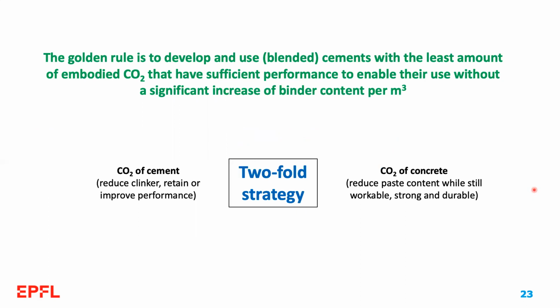Personally, I consider that the golden rule is that we need to develop and use blended cements with the least amount of embodied CO2, which in most cases is proportional to the lowest amount of clinker, but very importantly, that have sufficient performance to enable their use without a significant increase of binder content per cubic meter. And this is what I call the twofold strategy.